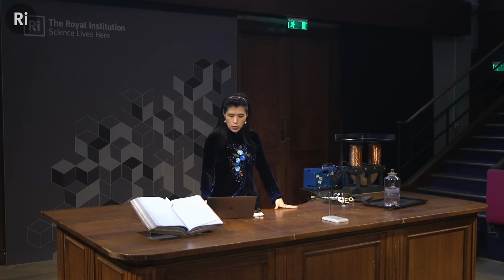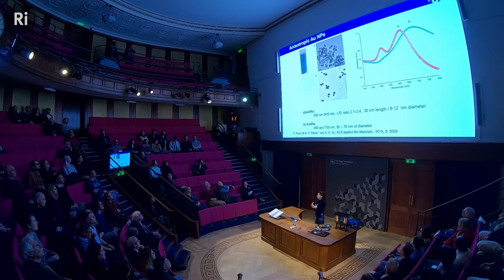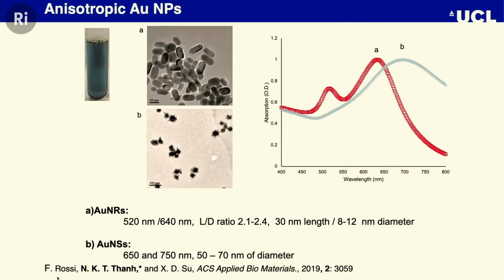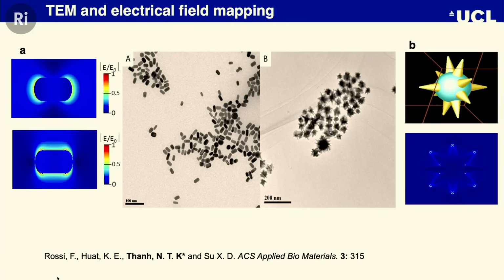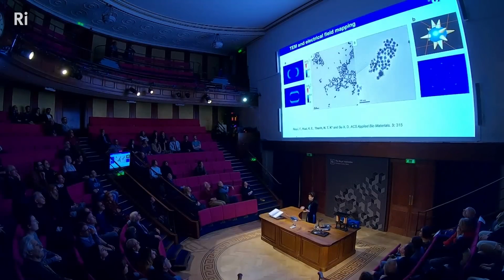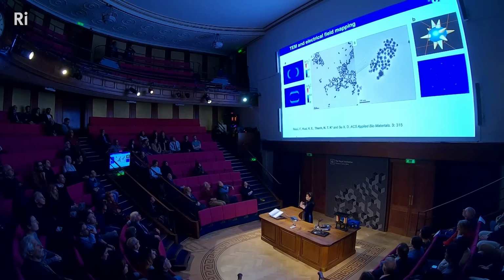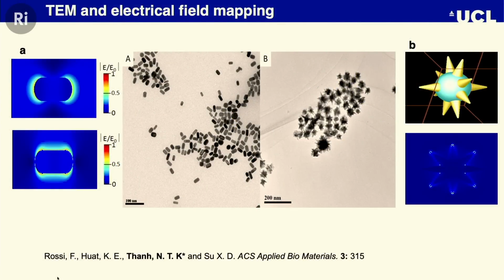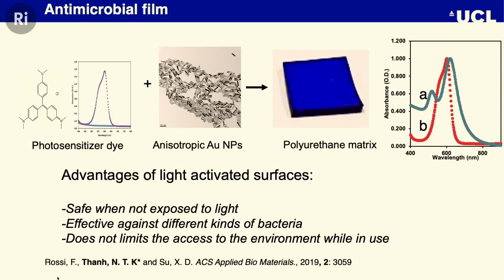So what we propose is that we could look into these gold nanorods and gold nanostars. So you can see the red spectrum is from the gold nanorod. You can see that typical peak there, and then also the gold nanostar. And the color of the gold nanorod is on this side that you see that I put next to the TEM. So we also look into the transmission electron microscope to see how they look, and also my colleague in Singapore looked into the electrical field mapping, so you can see how this plasmonic plays within the different structures.